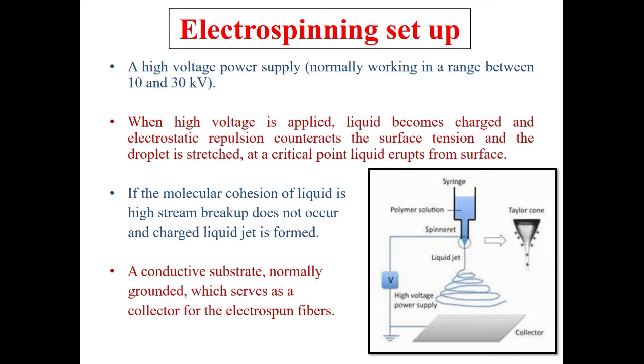It consists of a syringe, needle, high voltage power supply, and collector plate. When we talk about this particular setup, a high voltage power supply normally works in the range between 10 to 30 kilovolts, and that much voltage is required to draw the fiber. A crocodile pin is connected to the needle, and through that needle high voltage is given, and as the high voltage is applied to that needle, the liquid inside the syringe becomes charged, and the electrostatic repulsion counters the surface tension, and the droplet gets stretched.